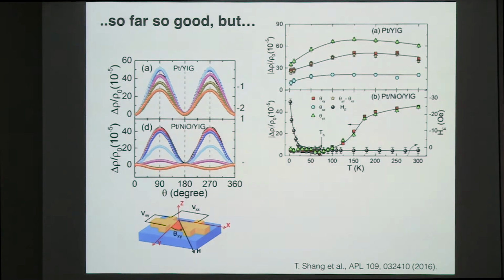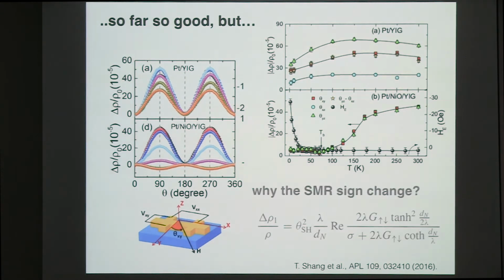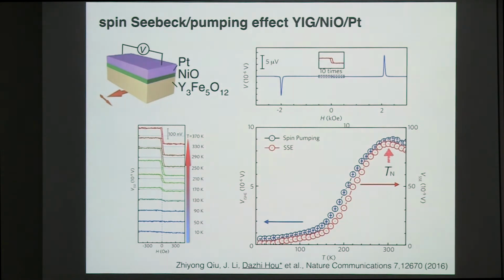So you can see it more clearly in the angle dependence measurement. This is pretty confusing because the SMR is defined to be positive. And actually, the people also show other systematic symmetry measurements and confirm this is SMR, but still with a negative sign. And that's very confusing for us. So I want to invite you to look at our previous data of the same structure in spin pumping. Because for the SMR effect, one condition for it to happen is that the spin current generated in platinum has to reach YIG to make this effect.